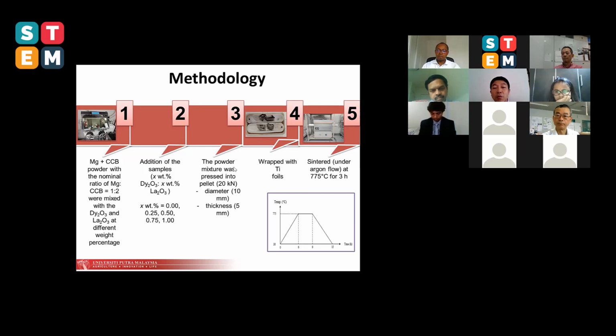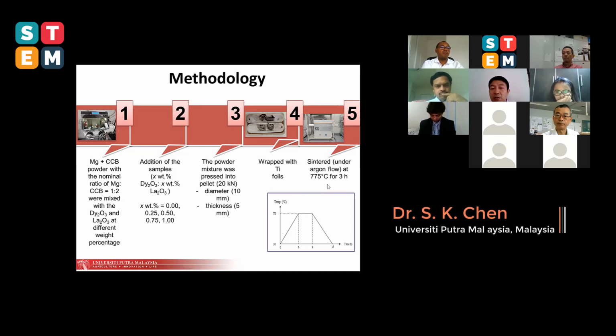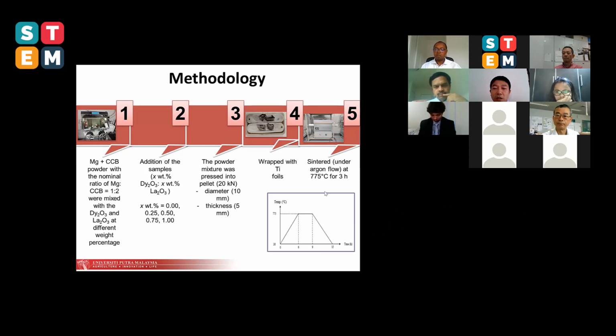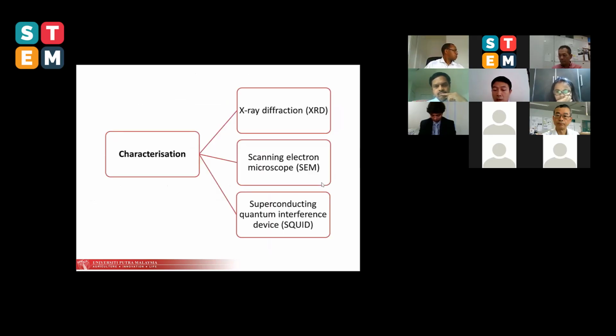After mixing, what we do next is to press those powders into pellets, and then we wrap those pellets with titanium foil, hoping to minimize oxidation. Those pellets were then subjected to sintering in argon gas flow at 775 degrees Celsius for 3 hours. Characterizations: I'm going to show you the results that we obtained from X-ray diffraction, scanning electron microscopy, and also from the SQUID measurement.